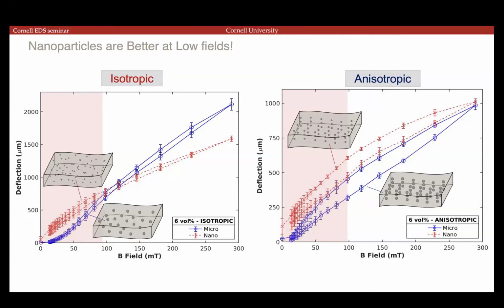So the one equation I didn't show is torque is M cross B. So if I apply a magnetic field orthogonal, then this high magnetization chain is going to bend. And then that'll force the entire film to bump up. So with the anisotropic films, hopefully if they maintain a strong magnetization or magnetic moment, we would be able to win in both of those cases.